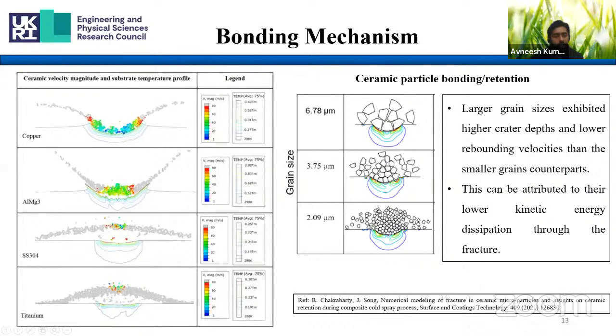However, they said that if jetting occurs at the interface, then the retention will not be there. This jetting will take the fragmented particle out from the surface. Then they also saw the effect of the grain size of the ceramic particle on the retention. For that, they took a titanium oxide particle and impacted it onto a copper substrate with different grain sizes. They saw that a higher grain size particle retains more after impact, and the reason they gave is that the dissipation of kinetic energy through fracture is lower in the larger grain size case.